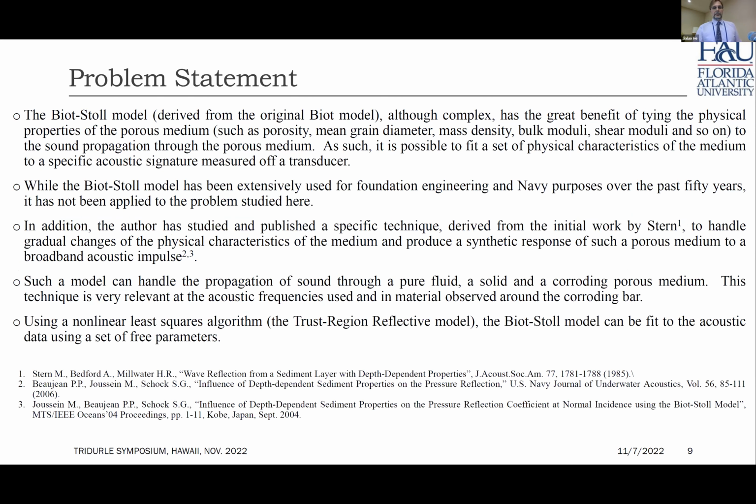So briefly, in terms of the problem statement, the Biot-Stoll model, although it is complex, has the great benefit of tying the physical properties of the porous medium, such as porosity, mean grain diameter, mass density, bulk moduli, shear moduli, and so on, to the sound propagation through the medium. And in addition to this original model, I actually published, as a past author, based on the work by Stern, the ability to handle gradual change in the physical characteristics of the medium.